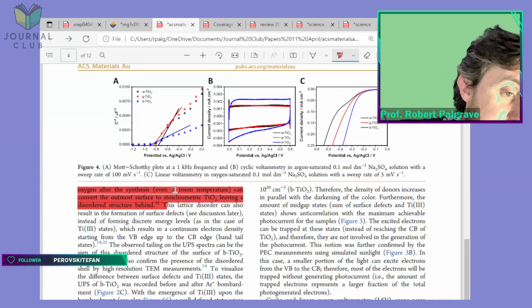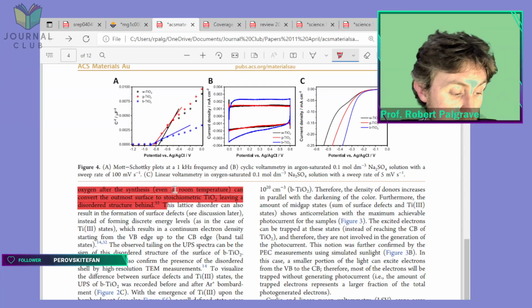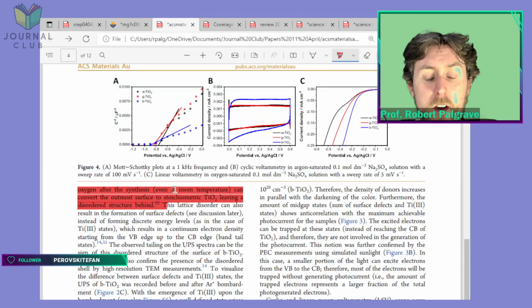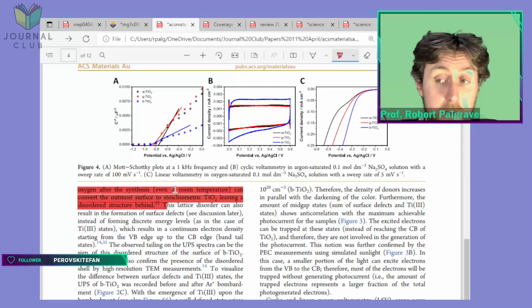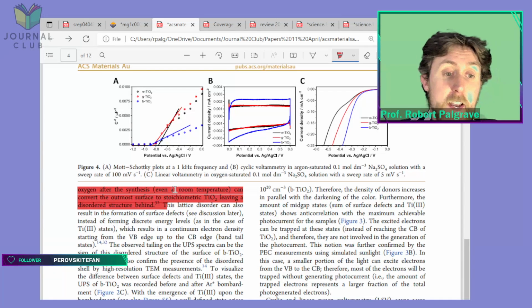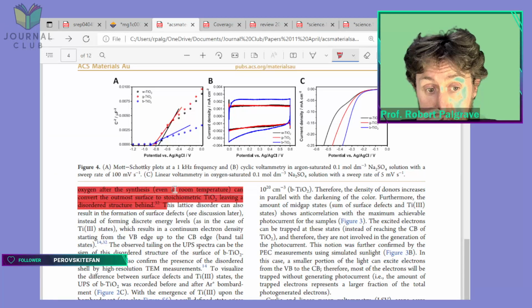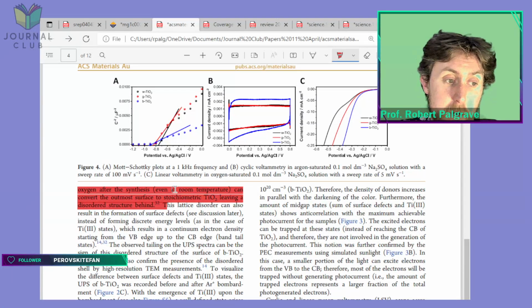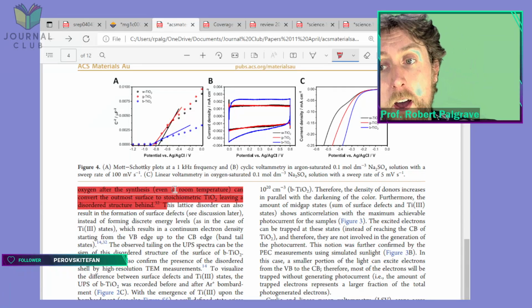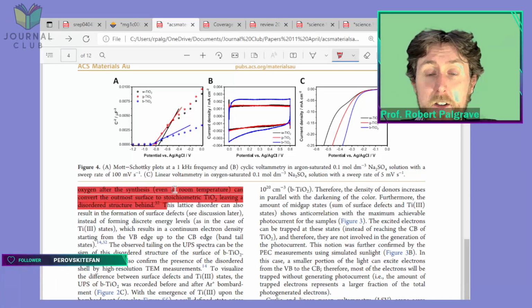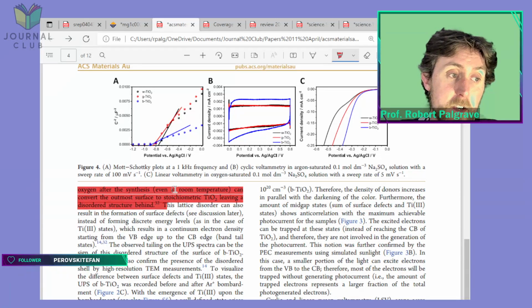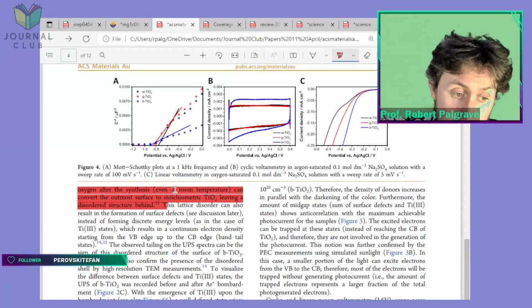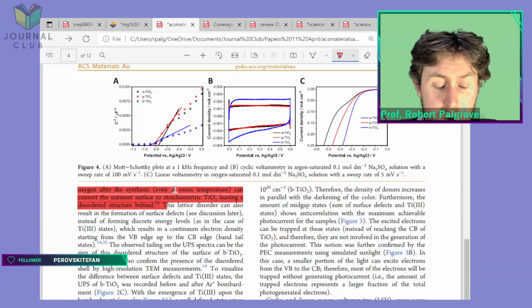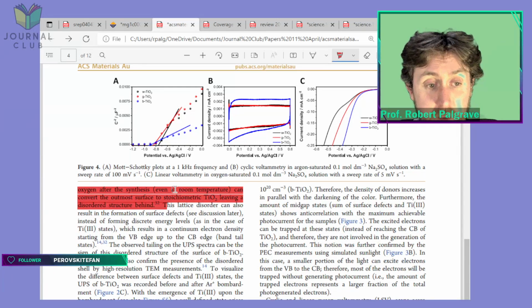So that's interesting, because I'm pretty sure that if you take Ti2O3, so titanium 3+ oxide, and handle it in air and measure XPS, you will definitely see Ti3+. I'm sure I've done this experiment. I know I've done this experiment. You will definitely see Ti3+. So it certainly isn't the case that Ti2O3 will be fully oxidized in the outermost 5 nanometers just by exposure to air at room temperature. So I'd kind of be surprised if this material is as well.